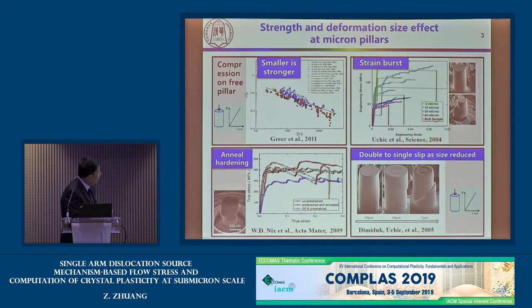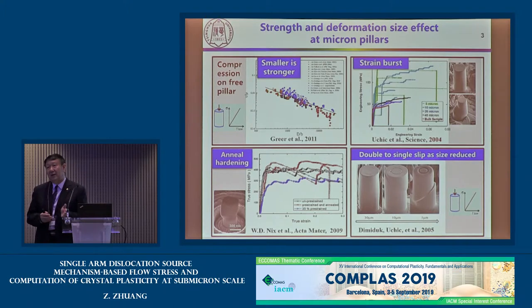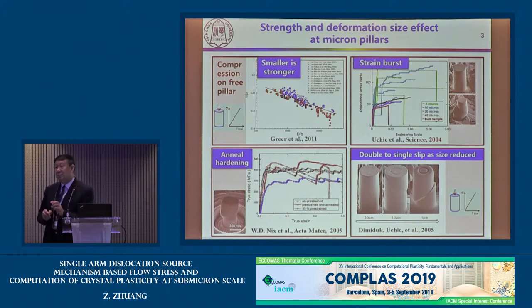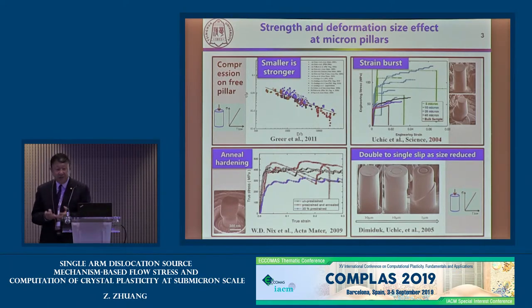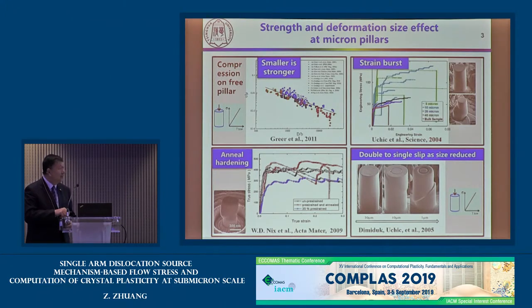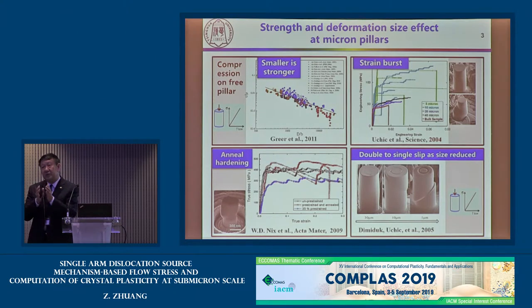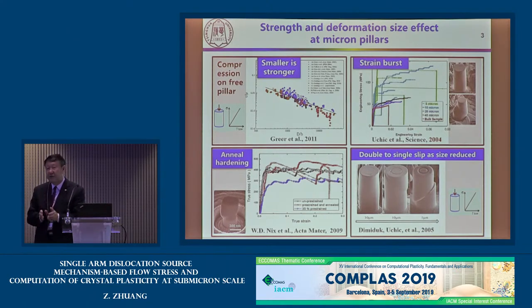Under these experiments, we need to find the mechanism — what happens in mechanical plasticity. Another observation is the deformation size effect in micropillars. From 30 microns to 1 micron, you can find a transition from symmetric to asymmetric deformation. As sample size is reduced, different deformation configurations appear, demonstrating the deformation size effect.